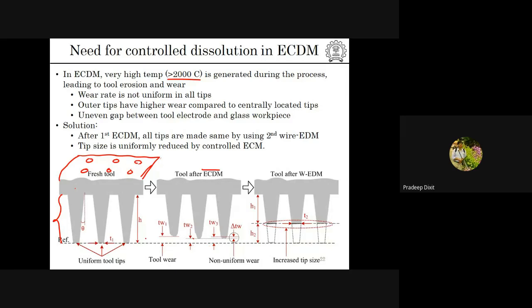So what we are doing here is, after the ECDM process, we do a second EDM process to cut and remove this particular part here, so all the tips are going to be of the same height. This is what we are doing in order to reuse the tool. But the problem is that although all the tips have the same height, this width is not the same as the width before. This width is going to be changed.